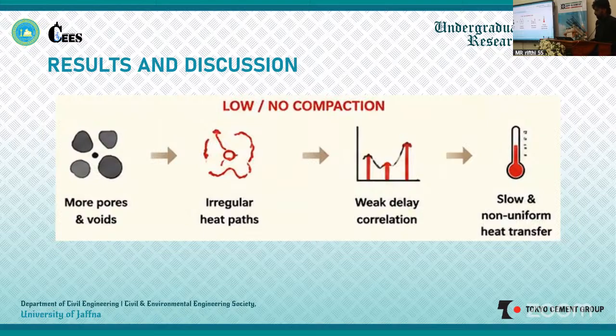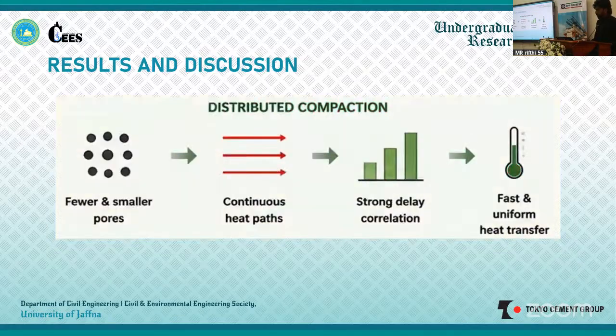Based on the results, these figures explain the heat transfer mechanism. In the low or no compaction condition, because of the large number of pores and voids, the heat follows irregular paths. As a result, the delay values show weak correlation, leading to slower and non-uniform heat transfer through the concrete. In contrast, distributed compaction reduces the pore size and makes the pore distribution more uniform. This creates more continuous heat paths, resulting in strong delay correlation, as we observed in the correlation matrix. Therefore, heat transfer becomes faster and more uniform throughout the specimen.